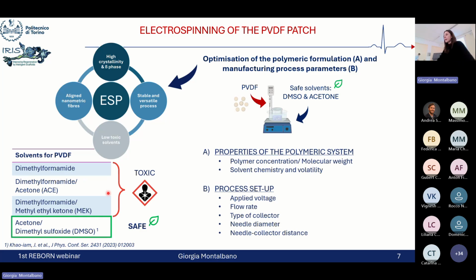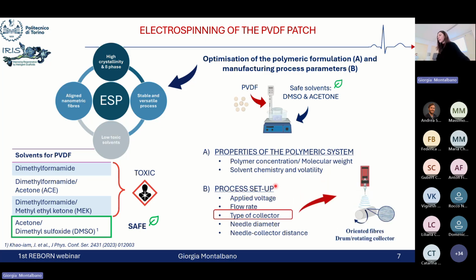So based on this choice, we then optimized all the other process parameters. Mainly the polymer concentration was optimized according to the fact that we need a very stable process for a long time. So we combined these optimized parameters with all the other process parameters in order to properly balance the applied voltage, flow rate, needle diameter, and needle collector distance, where as the collector, we selected a drum rotating collector in order to induce the alignment of the deposited fibers.